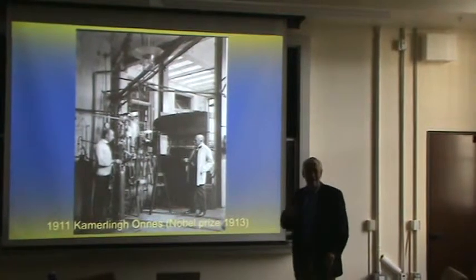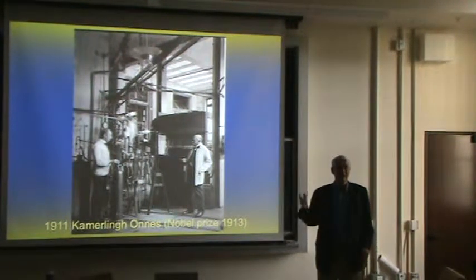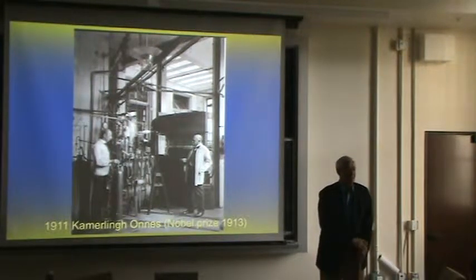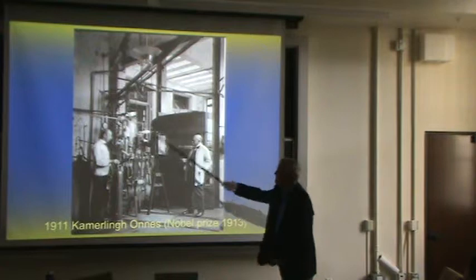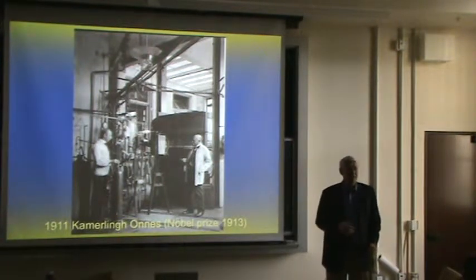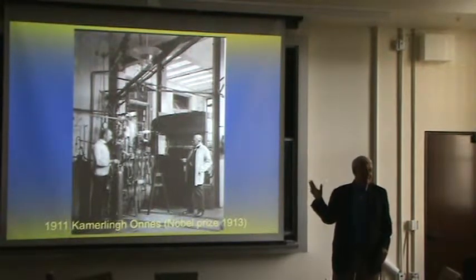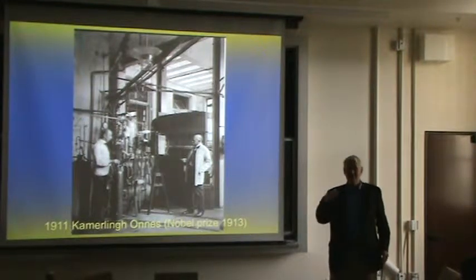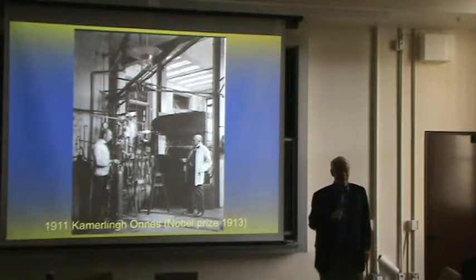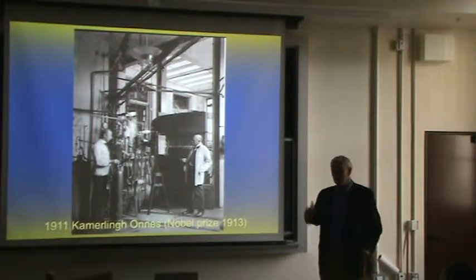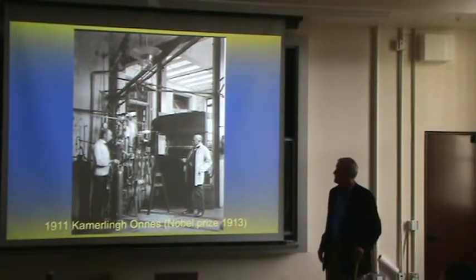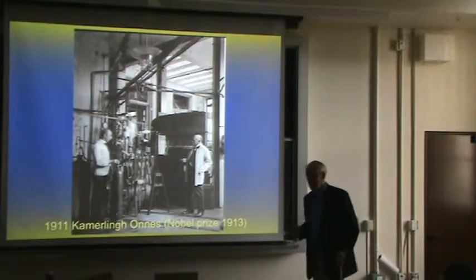But anyway, his goal was to liquefy helium gas, to see if you could turn it into a liquid. All of this apparatus was based on the Joule-Thomson effect to liquefy helium. And they succeeded, so they were the first people on the planet to liquefy helium. At atmospheric pressure, it liquefies at 4.2 degrees Kelvin. So this meant you then could have samples at 4.2 degrees Kelvin, and if you pumped on the liquid, you could pump it down through the superfluid transition, actually down to just above 1 degree. So this was an extraordinary technical achievement.